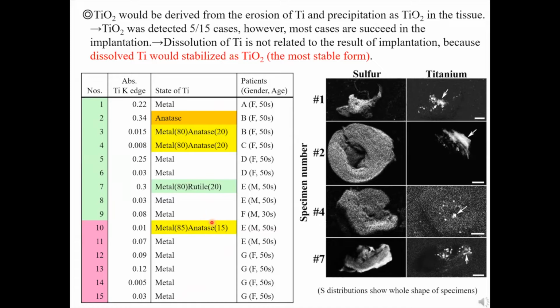Dental implant fixtures nowadays often have thick anodic oxidation layers. However, as mentioned before, the tested implant is a conventional Brånemark type 2 implant, which has a machined metallic surface. So, the accumulated titanium oxide was not directly derived from the implant surface. We assumed that titanium oxide would be derived from the erosion of titanium and precipitation as the oxide in the tissue, because titanium oxide is the most stable species.